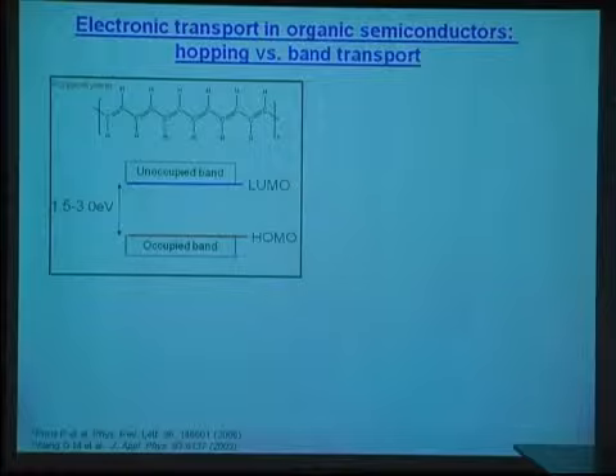So let me talk a little bit about the transport in organic materials. Let's consider a single chain, a polyacetylene chain. As you can see here, we have many pi electrons. Those pi electrons form bands in the single chain like this. The lower band is fully occupied and the upper one is empty. In the language of molecular orbital theory, the red line here is the highest occupied molecular orbital, the HOMO, and the blue line here is the lowest unoccupied molecular orbital, the LUMO. The gap between the LUMO and HOMO is about 1.5 to 3 electron volts, depending on the length of the polymer that we have here. So these are very good materials for light-emitting diodes, because the gap is in the visible range, and also for organic solar cells.